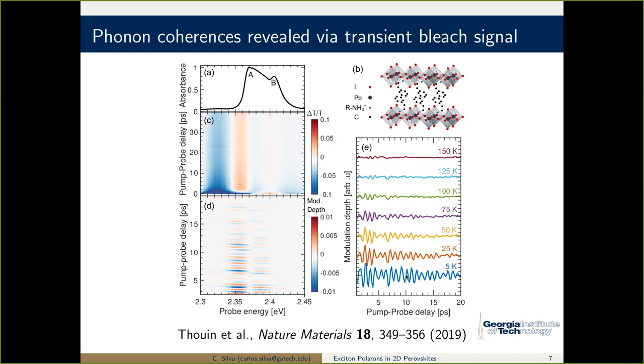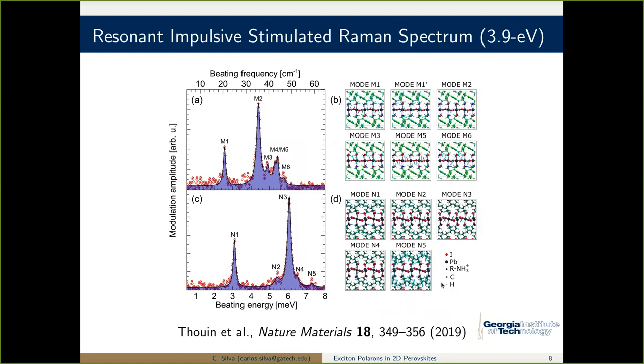These wiggles, those contain spectral information. There's a temperature dependence, and let's just stick to 5 Kelvin for the moment, just for time. So I can take a Fourier transform of this, and this is basically a resonance Raman spectrum. So over this very low frequency range, this is a resonance Raman spectrum of all the normal modes, the phonons that are coupled to the photocarrier. I inject photocarriers, the crystal starts wiggling, it starts dancing, and it is those phonons that are coupled to the photocarriers that show up in the spectrum.